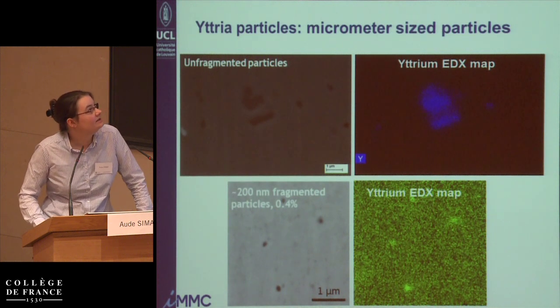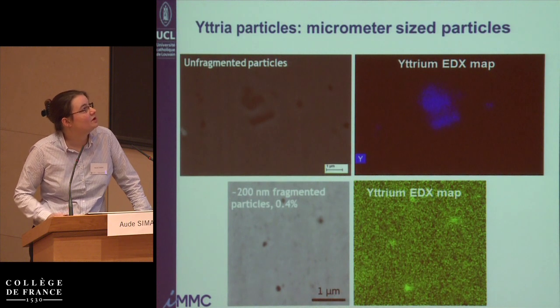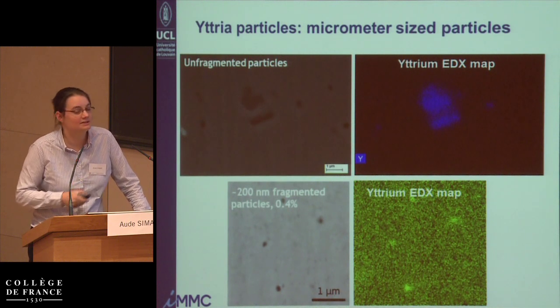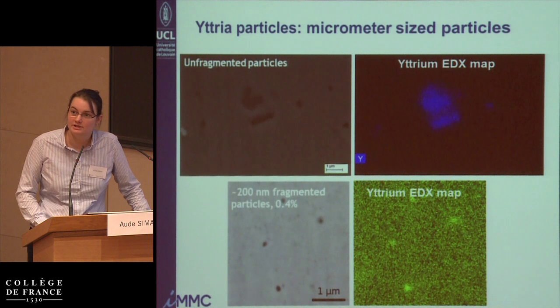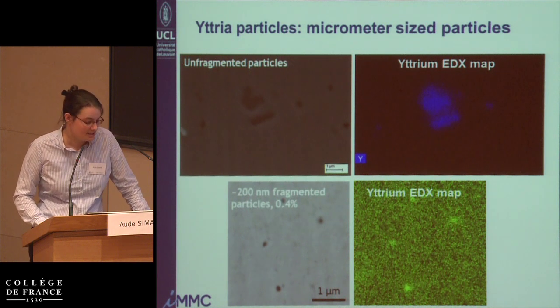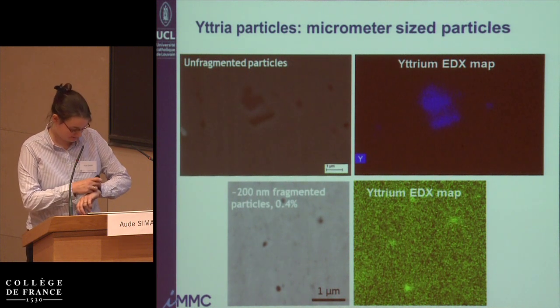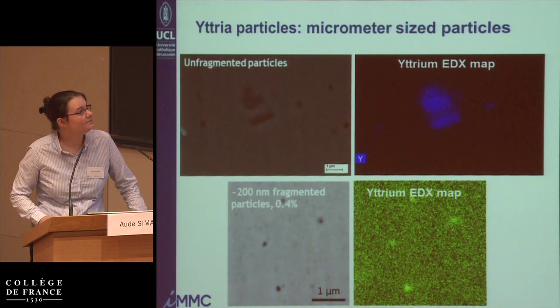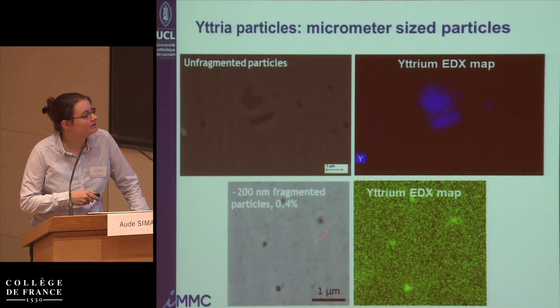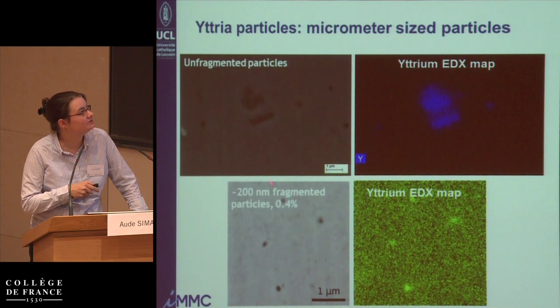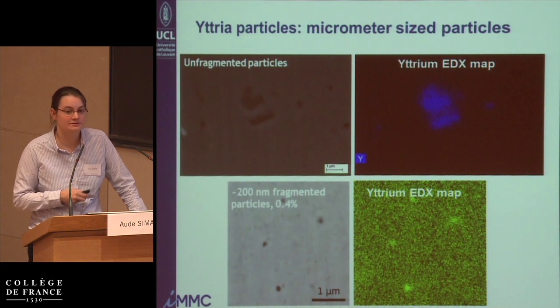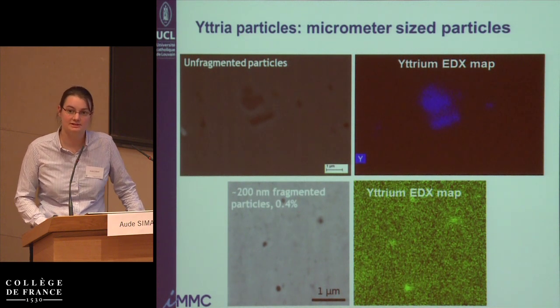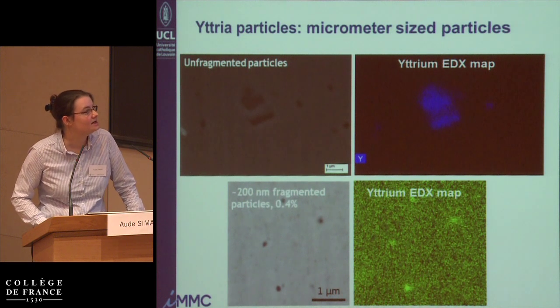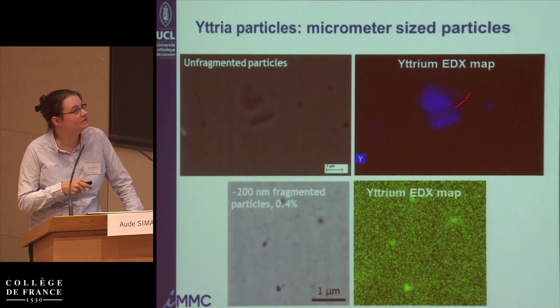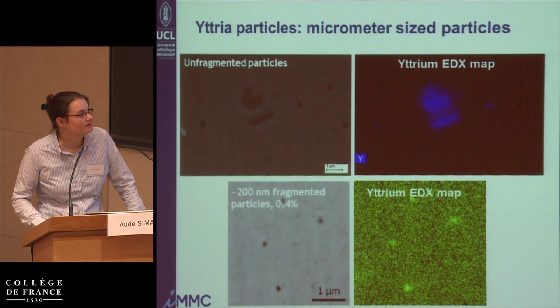deeper scale, and see that we have some unfragmented particles that are pretty much the size of the initial yttrium oxide, and some particles that are fragmented parts of this particle that have been fragmented by the large plastic deformations that you have in the material. And so these are EDX maps to identify these particles as yttrium oxide.